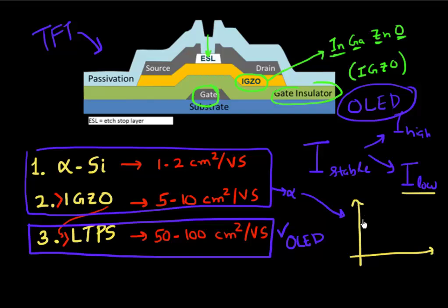So there's a lot of VT instability and there's a random capture of electrons which happens in these amorphous materials, especially when your current is low. It fluctuates quite a lot in these amorphous materials. So these are ruled out for OLED-based display.